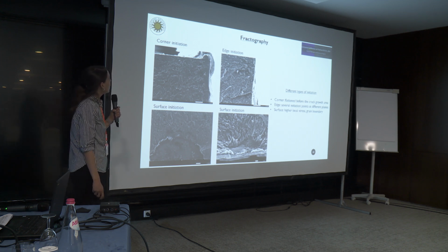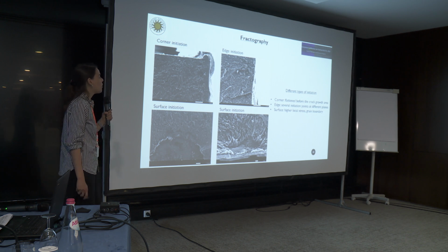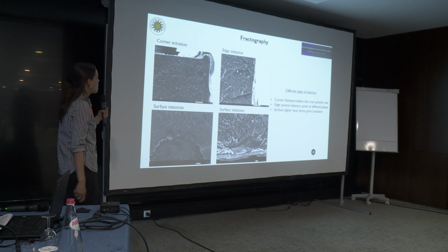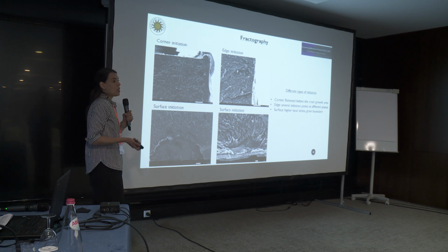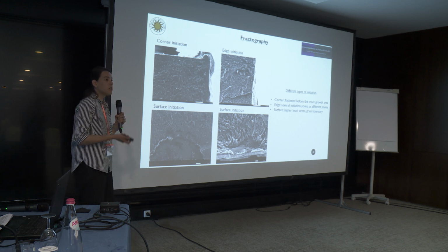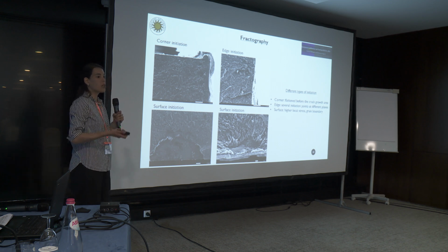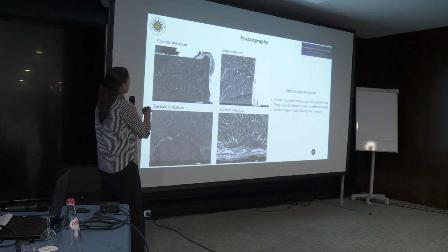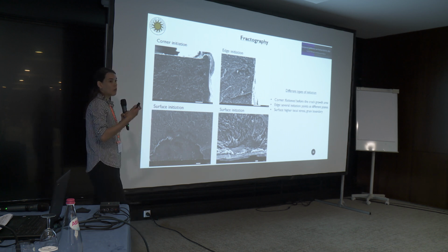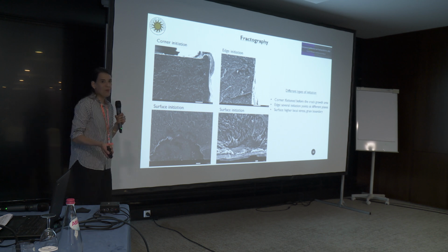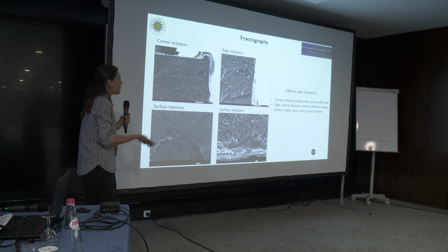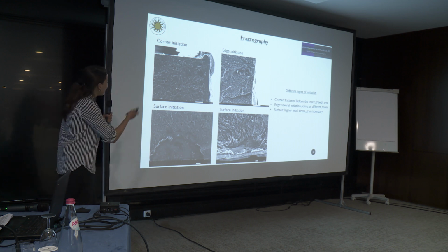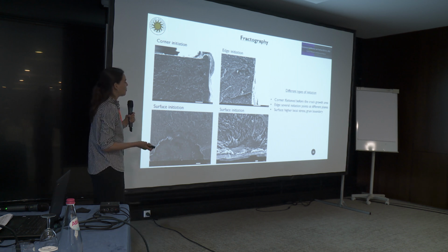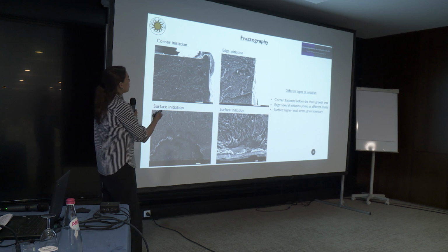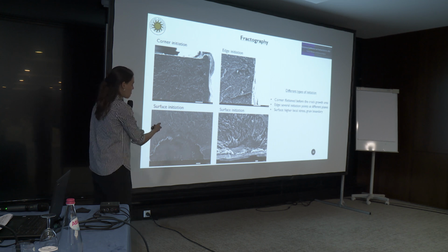A little bit more detail about the initiation points. We found different initiation points, starting from the corners or at the edges, and of course some surface initiations. At that point, I would like to say that the specimens had high tensile strength, so in order to reach our dimensions, they were cut by EDM. So probably the corner and edge initiation points are correlated to the EDM process, even though we tried and polished them, I believed very well, but it seems not so well. However, we also have surface initiation points correlated to higher localized stress and/or some microstructural features like grain boundaries.